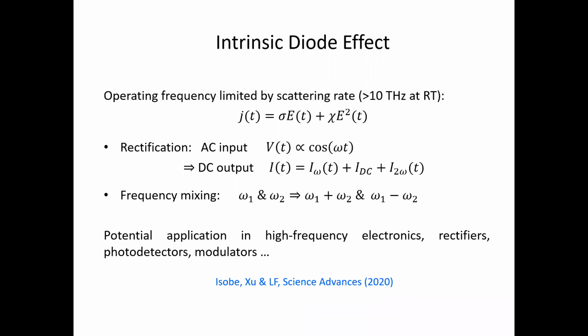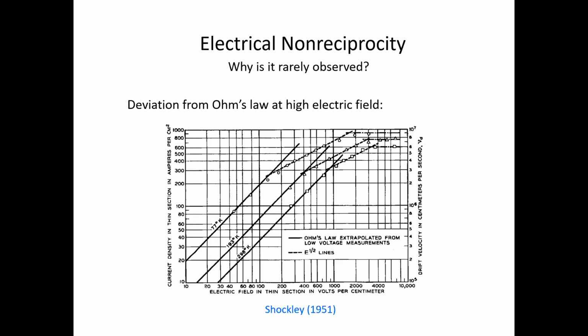A few years ago, we started thinking about this. Now, the problem is that most materials, if you measure their IV characteristic, just follow Ohm's law. The correction, even though it's allowed by symmetry, is very rarely observed. This is not to say that a nonlinear IV curve has not been seen before. In fact, I was looking at the literature from more than 70 years ago at Bell Labs: this is a measurement of a germanium crystal, the IV curve at high electric field and large voltage. In this case, you do see a deviation from Ohm's law.